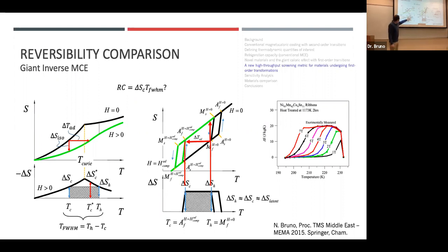Notice in the left diagram, we just have this rectangle underneath the delta S versus T curve. And on the right side, I didn't shade the region in the thermal hysteresis, right? Because that's not a reversible temperature region where we can cycle field and get the same thing again and again. So I don't think we can simply do full width half maximum for shape memory alloy. That would actually encompass the entire diagram.